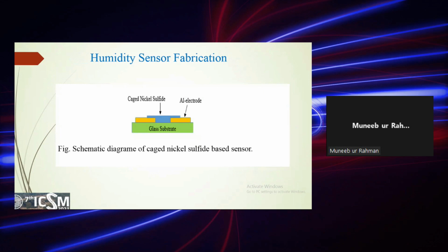So, humidity sensor fabrication. First of all, we prepared the solution of cage nickel sulfide, and then we drop cast it between the two electrodes already deposited on the glass substrate, and then we made an electrical connection, and we measured the capacitive and resistive response of the cage nickel sulfide material when the humidity in the chamber is increased from very low humidity to very high humidity, up to 95% humidity.